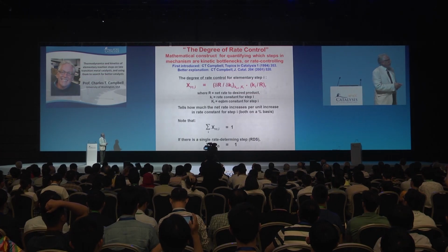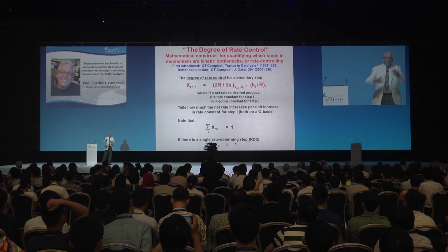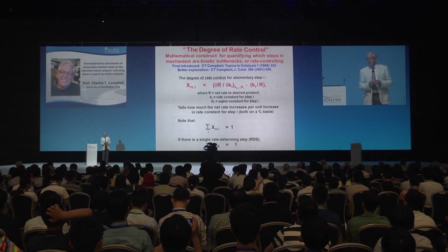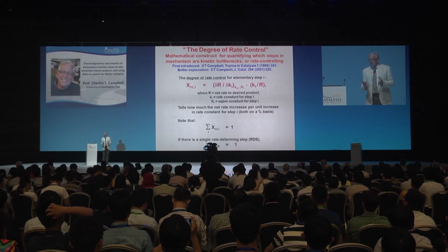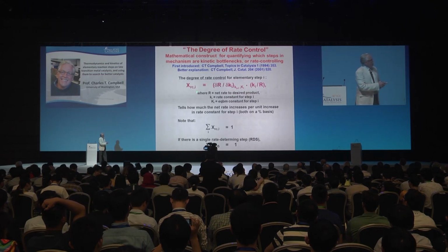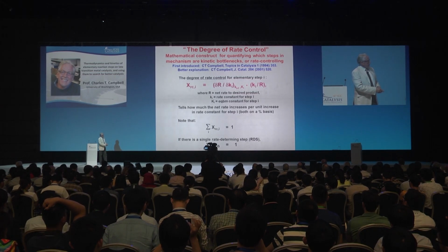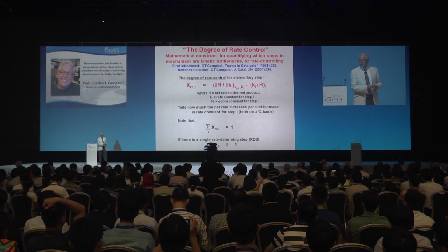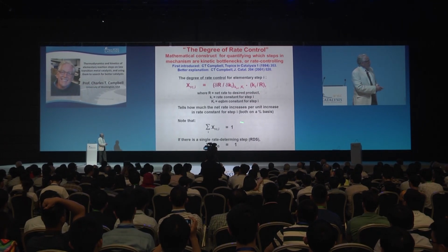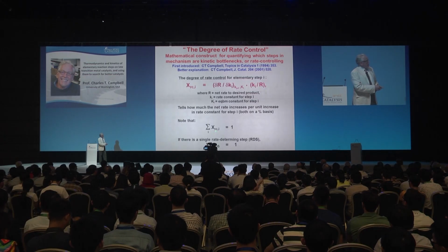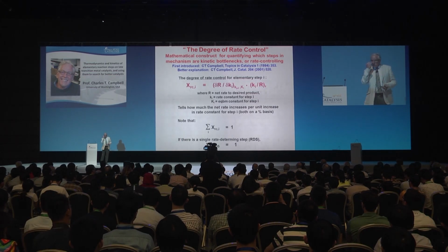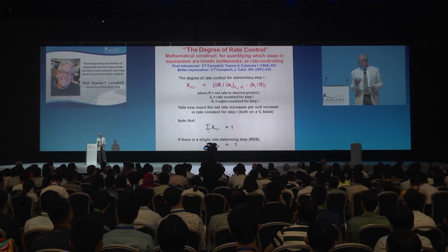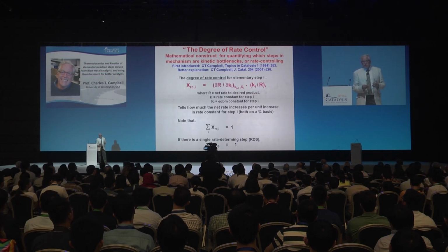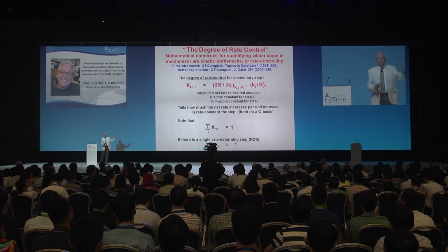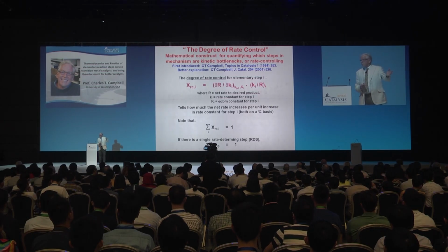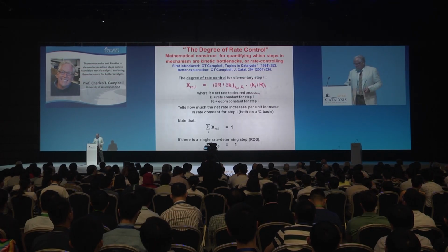And it turns out if you have a simple mechanism where you can work out an analytical rate expression and it has a single rate determining step, then if you do this operation, you discover that the degree of rate control for that rate determining step is 1. And you also find for sequential reactions at least that the sum of the degrees of rate control for all the elementary steps is 1. So for simple analytical rate expressions, it's common to have the degree of rate control 0 for all the elementary steps except for 1, and the rate determining step has a degree of rate control of 1.